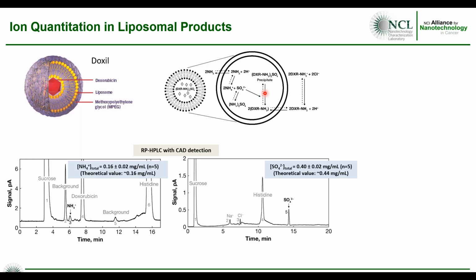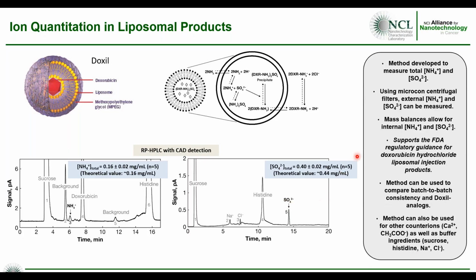So we came up with a reverse phase HPLC with CAD detection to quantitate ammonium as well as sulfate. These are the total amounts. And then using Microcon centrifugal devices, you can actually measure the external amount of ions. And then through mass balance, you can calculate the internal concentration. This methodology does support FDA regulatory guidance for doxorubicin hydrochloride liposomal injection products. We use this a lot to compare batch-to-batch as well as to assess Doxil analogs. And then this method can also be extended for other counterions as well as excipients or buffer ingredients. And we published this in the paper shown here, which basically details this methodology.